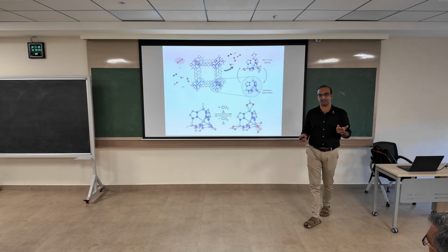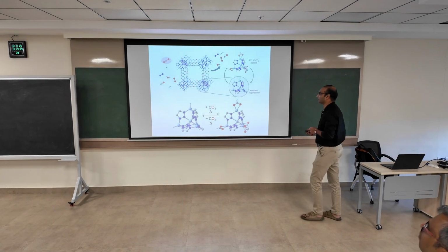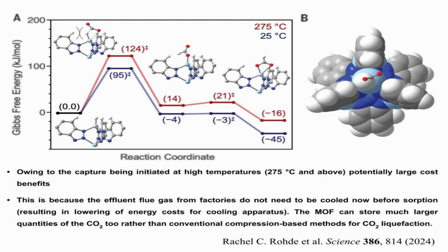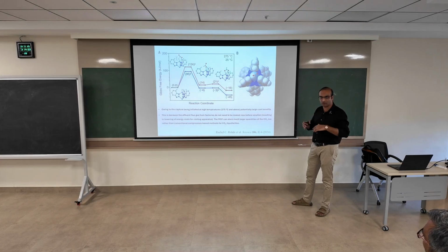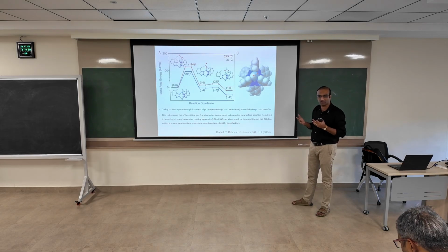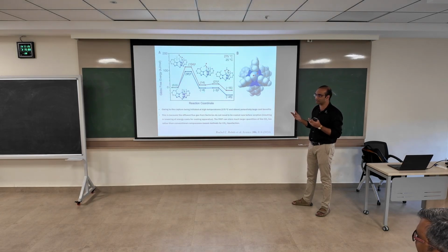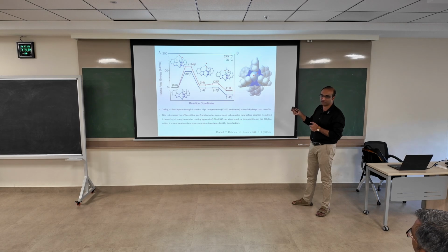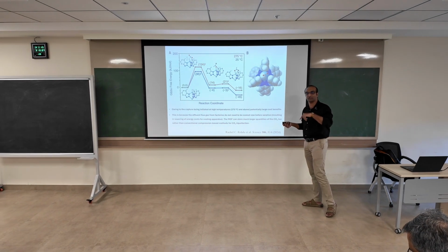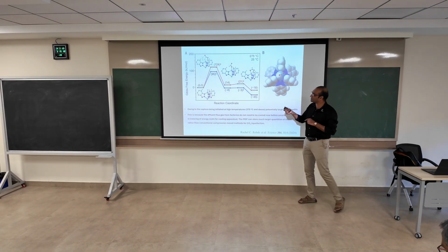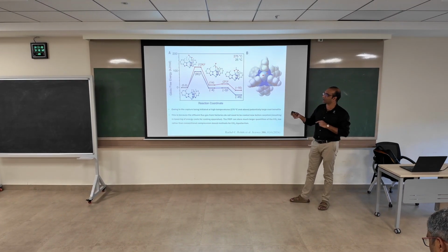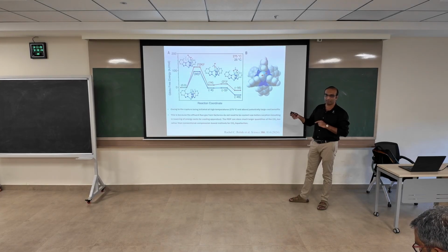Very low temperature. You don't have to heat at a very high temperature. But the advantage of this process is it happens at around 275 degrees Celsius. See, at 25 degrees Celsius, it doesn't happen, right? Like when I told you guys about the amine, you had to cool it down. Here again, you don't have to cool it down at all. Sometimes the flue gas stream can be even hotter than what we expected, like 200 or 300 degrees Celsius. This MOF becomes active only at 275 degrees Celsius because at this temperature, it can overcome any thermodynamic barriers and actually adsorb it. The energy requirement is not that much compared to when you do that at 25 degrees Celsius. Okay.